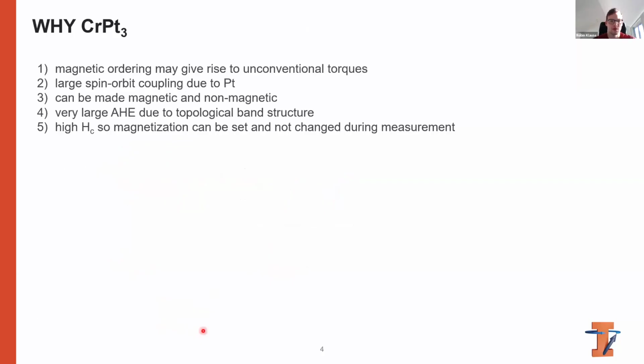The material that we're interested in is chromium-platinum-3, for several reasons. The first is that magnetic ordering may give rise to unconventional torques, just like in the ferromagnetic case. I should also mention that chromium-platinum-3 is a topological semi-metal.